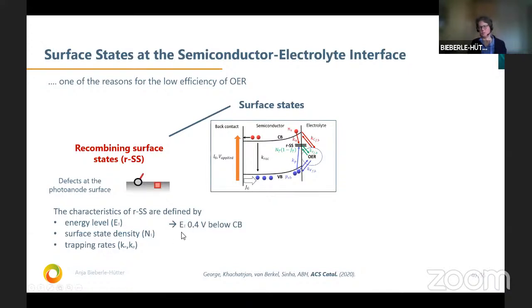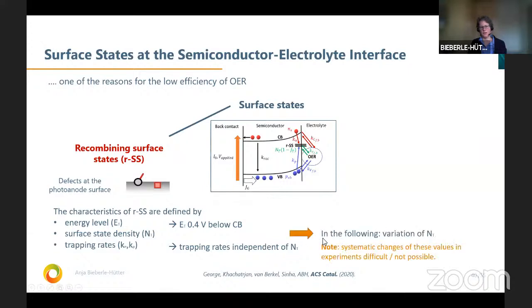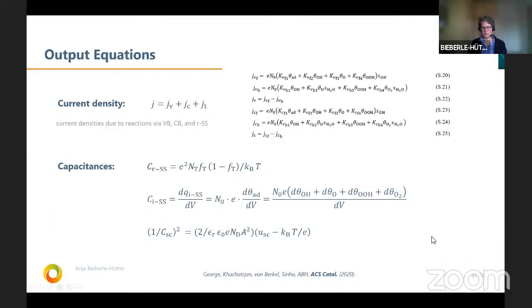So we assume now that the energy level is 0.4 volt below the conduction band. We have this from the literature. We assume that the trapping rates are independent of the surface state density. And what we can do now in the simulations is change just this parameter. And this is the nice thing compared to the experiment, that we can really systematically change this parameter. In an experiment, it's not easily possible.